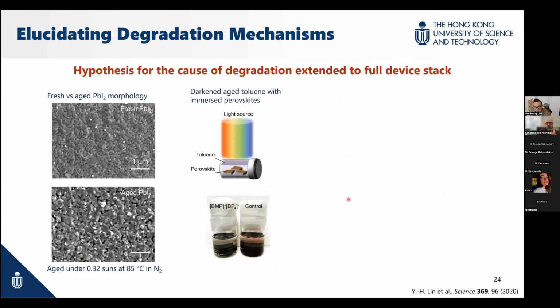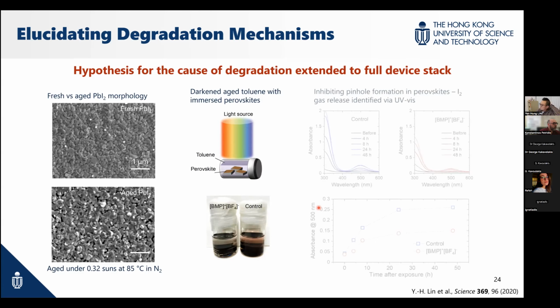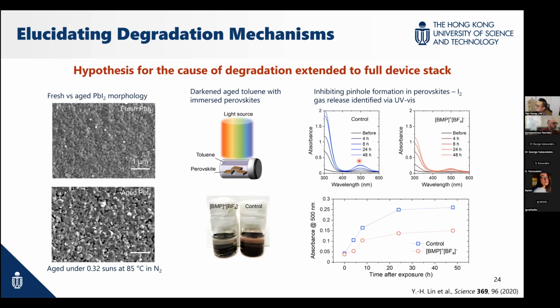Then we tried to double check if this is what is happening. So we prepared a perovskite and put it in toluene. We sealed the vial. We put it in an aging machine, just like these two. So one is modified, the one is control. This is after a while, but you can see the color is different in toluene. So exactly what happens. We did some UV measurement, and you can see a peak coming out at 500 nanometers. It fits the feature of iodine. So lead iodide is not likely to be the degradation product in this scenario. Why is this the case? Actually, when we buy lead iodide, we are told, oh, we have to avoid light, it's a sensitive material.